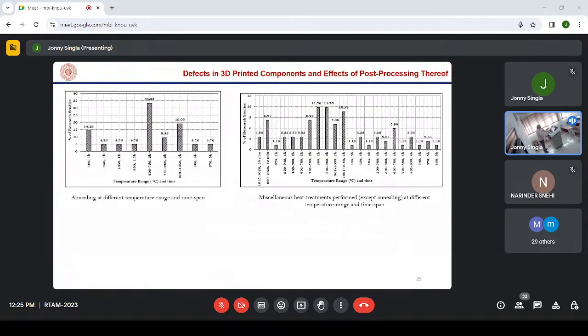Now these are the various heat treatment temperatures used by different researchers, and it has been found that the range from 600 to 750 degrees Celsius gives the best results for post-processing. That means whenever you manufacture a product using AM techniques, you do post-processing heat treatment in this range of 600 to 750 degrees Celsius. This may vary a little for different materials, but this is for titanium. From 600 to 750 degrees for 2 hours gives the best results.